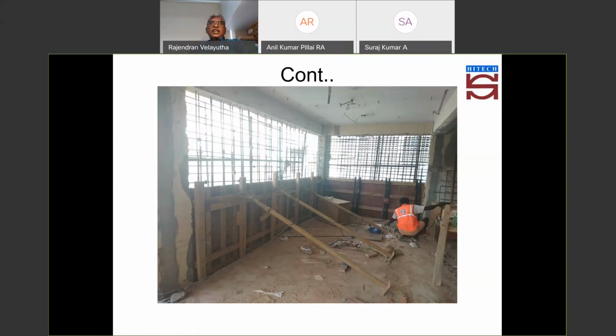Out of this, 320 kgs with the cement and 130 kgs with fly ash, and we were able to get 650 millimeters spread, and then we were able to pack up. In addition to that, we also added the aluminum powder where we don't want the shrinkage to take place between the soffit of the beam and the new concrete which we are going to lay.